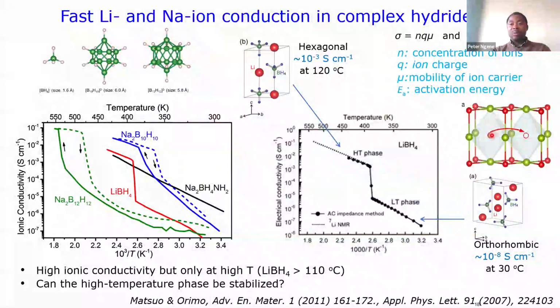And I try to show here, basically, if you want to measure the ionic conductivity of a material, this is given by the concentration of the defect, because this material works based on defects. So if you have a crystal structure and then you have a defect, which in this case is a vacancy and interstitial site, then you have the hopping from here to here within the crystal structure, which gives rise to the fact that this ion can move. This is lithium plus, and it can move into this vacant site, and by doing that, you see there is basically ion mobility in your material. So it is based on the number of these defects that you have there, and then also the mobility of the ion carrier, and then the activation energy, which is the energy that you require to jump from one place to the other. So basically, this is what you need to understand.